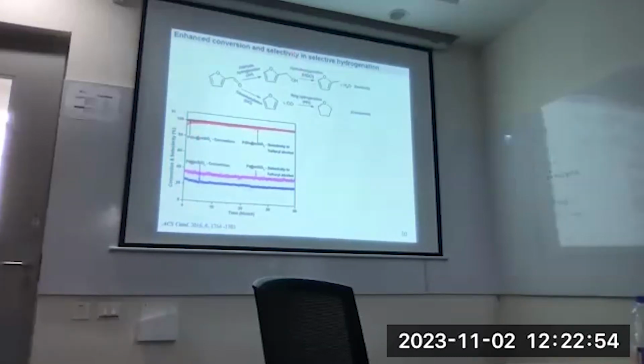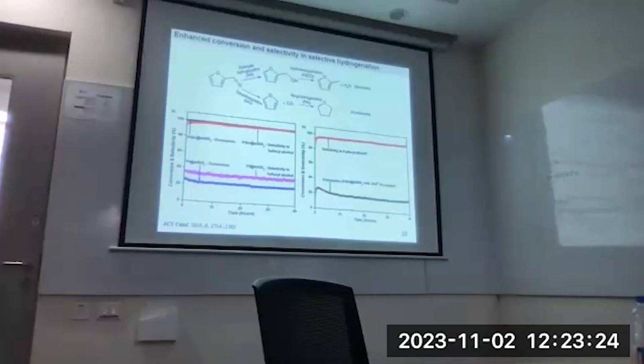Where I use only platinum tin, I get only this product. Okay. Whereas when I'm using platinum, my selectivity to this product is only around 36 to 37%. Okay. And the conversion is also low. So in the case of platinum, I'm getting this, this, this, and this. And I'm even getting compounds that are completely broken down, like linear chain compounds. Okay. So you cannot control it on the surface of platinum. Whereas just by introducing tin, I'm selectively getting only this product. Okay, and even when I reduce the amount, like using 1/10 the quantity of platinum, I can get the same activity as just platinum. So again, I'm enhancing the usage of my precious metal. Okay. And the selectivity still remains almost 100%. I only get this product. I don't get these other products.